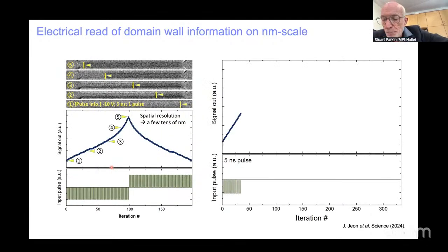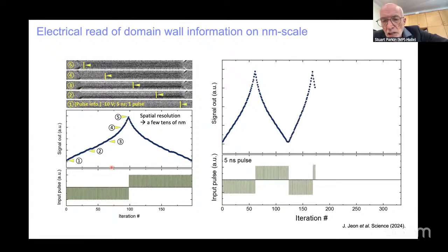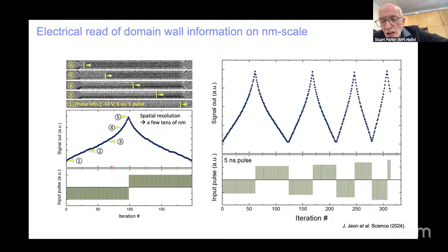And this is what we did here. This is a paper we published just at the end of last year in Science. And in this paper, we demonstrated that we could follow the motion of one domain wall as it's moved by current pulses from one end to the other of a racetrack. In this case, you can see that the current pulse is shown at the bottom. They're either in the negative direction, the domain wall moves from the left to right, or the positive direction, the domain wall moves from the right to the left.